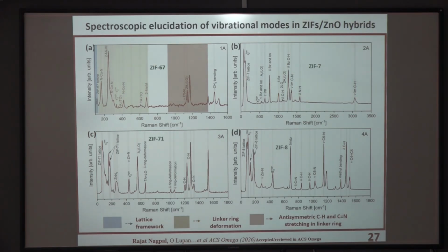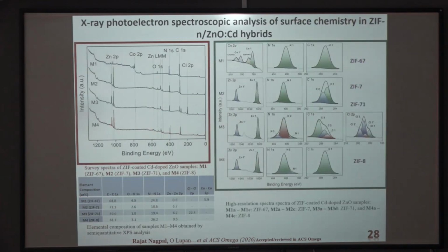Now, to get insights about the phonon modes, here we can see micro-Raman spectra among these hybrids classified in 3 different regimes, starting with the blue regime corresponding to lattice framework vibrations mentioned over here, and in the yellow regime linker ring deformation based phonon modes, and at higher wavenumbers we can see antisymmetric stretching and the imidazolate ring.